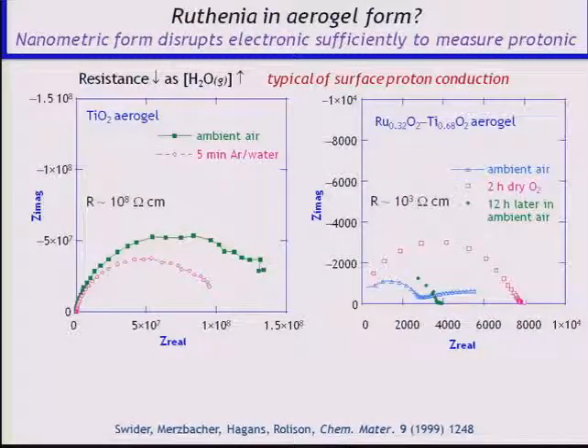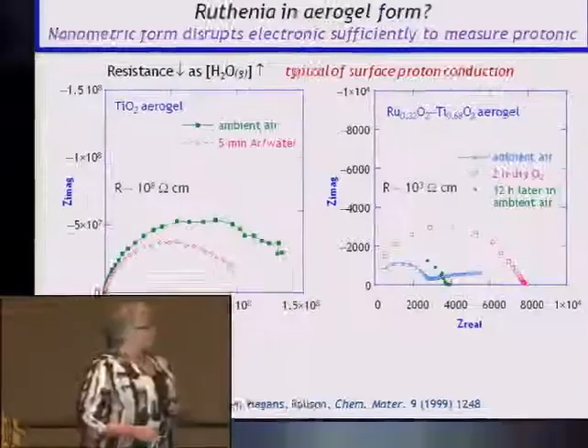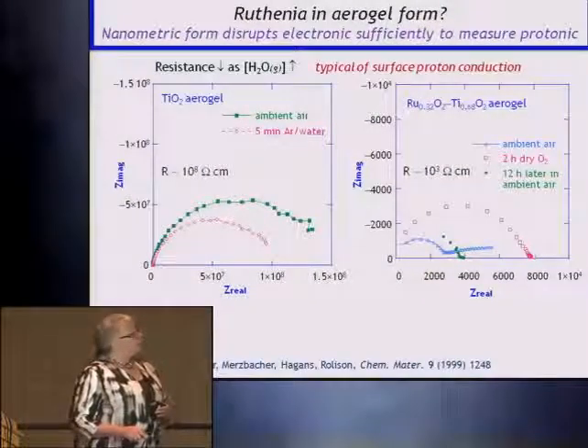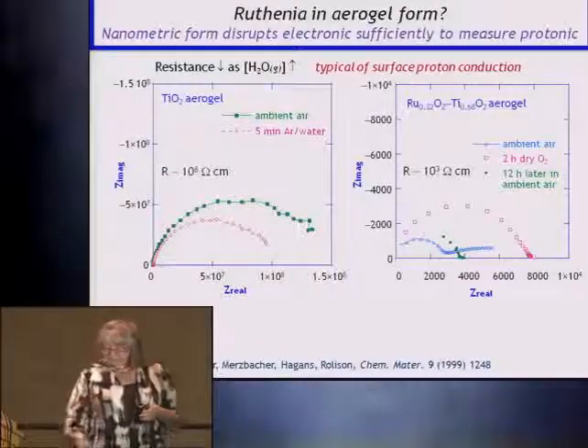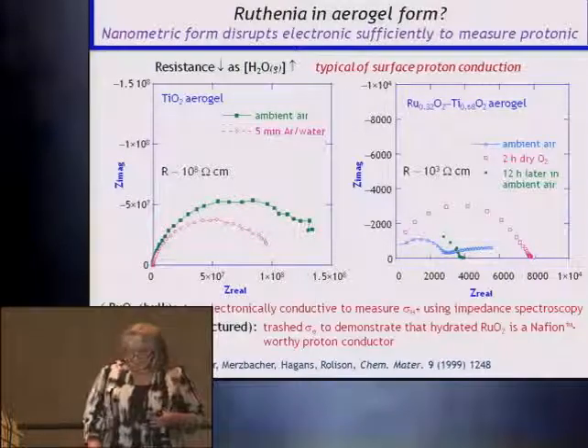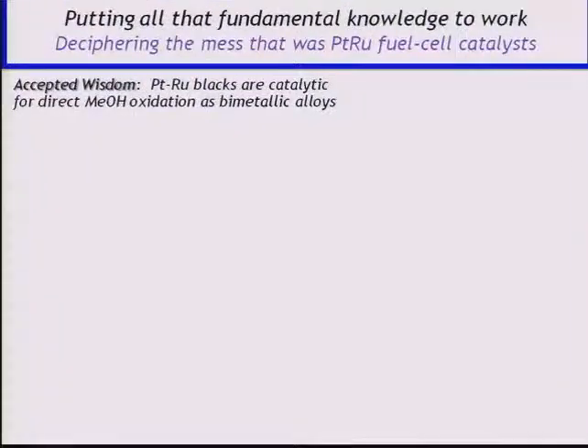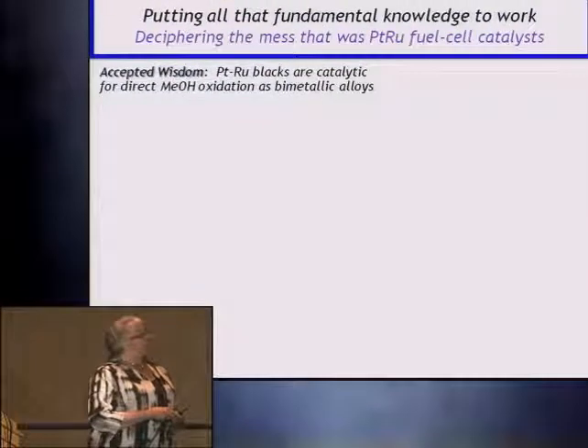You dry it out, which is this pink-red curve here. You become less conductive, more resistive. You give it more water, it gets less resistive. So again, the proton is moving in this system. And that was of importance to us because we were trying to also do work funded by DARPA to understand platinum ruthenium catalysts used in direct methanol fuel cells.